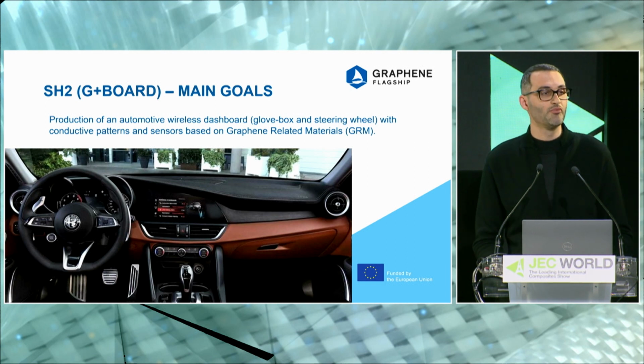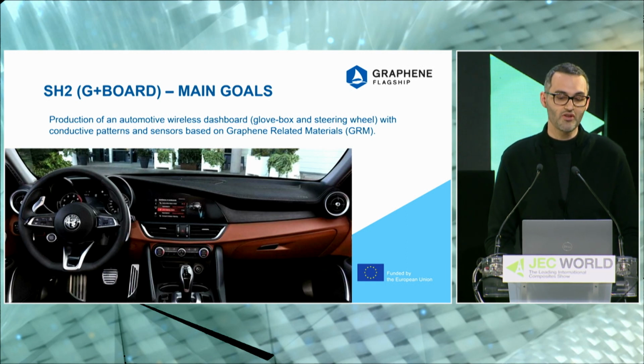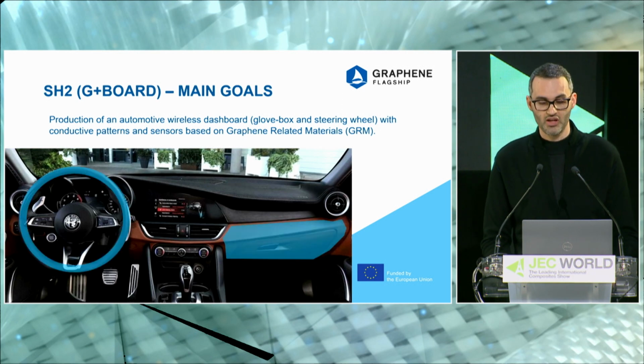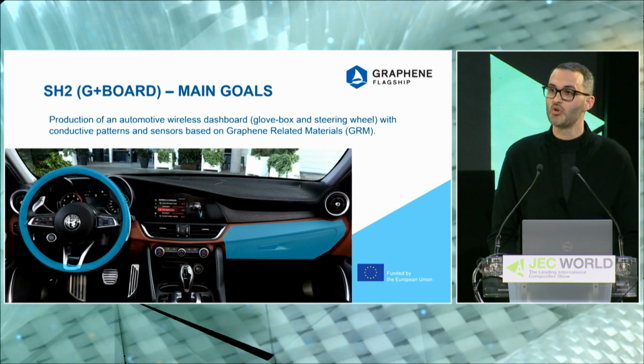So in fact, this is the project inside the project that we developed during the Graphene Flagship. It is called G+ board, and it uses graphene-related materials in order to have a dashboard which has two multifunctional components: one steering wheel which can be heated, and a dashboard drawer with sensing inside. Specifically, we are using graphene for the two applications in two different ways. For the glove box, for the dashboard drawer, we are using an engineered PP, which is filled with graphene.